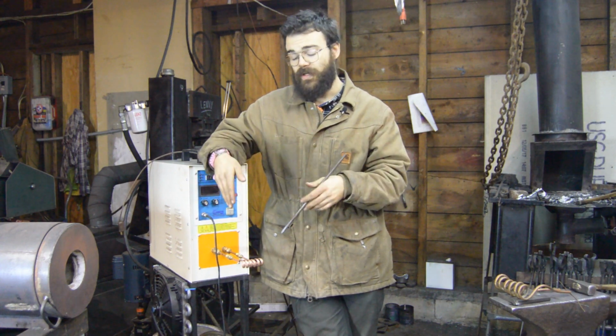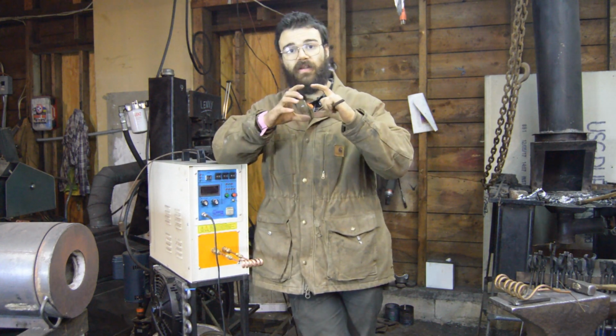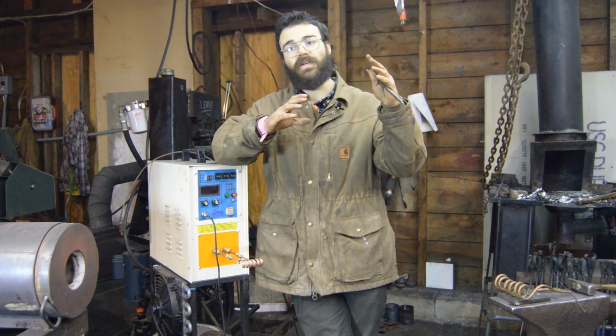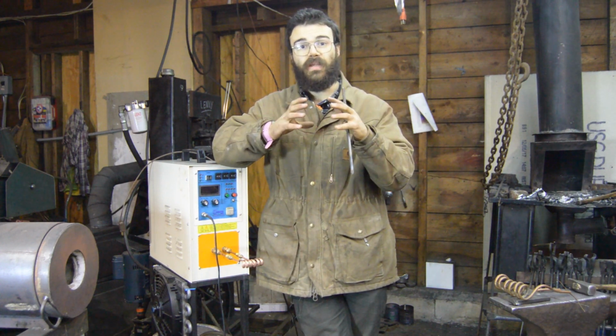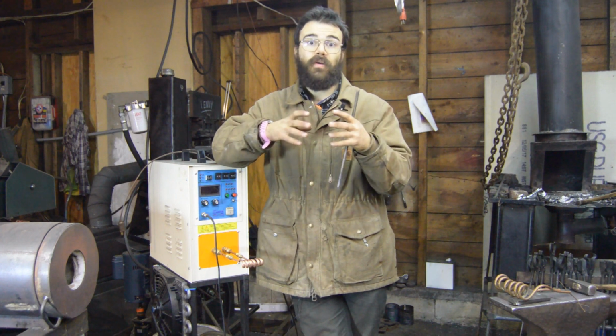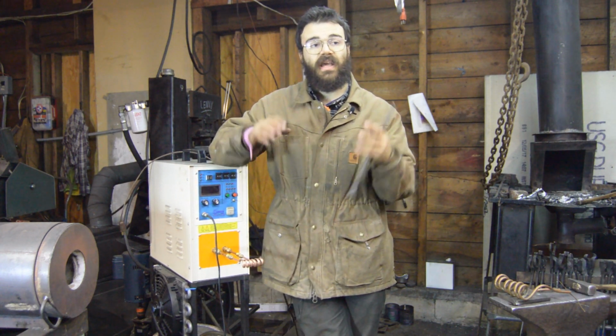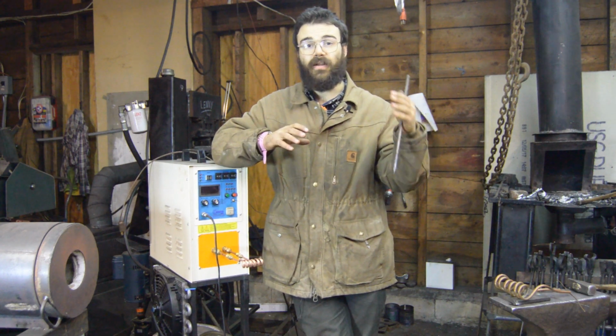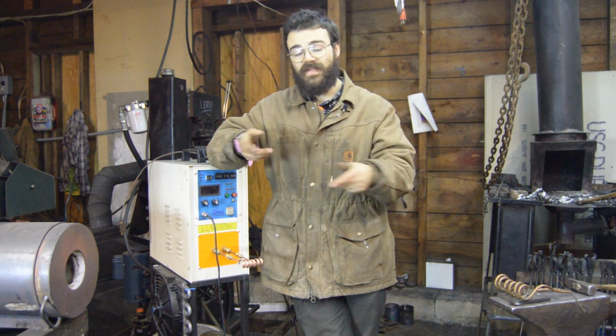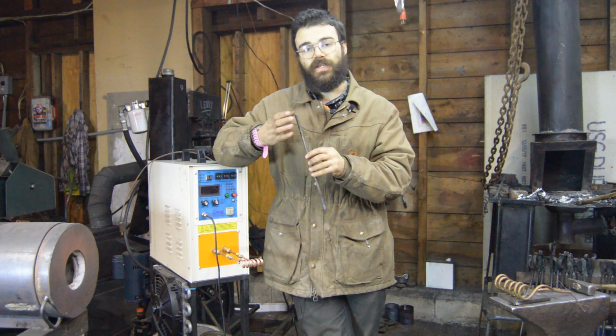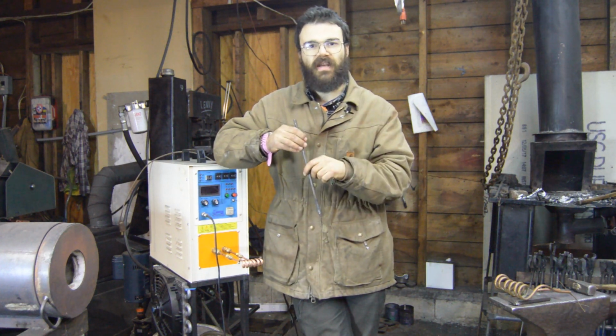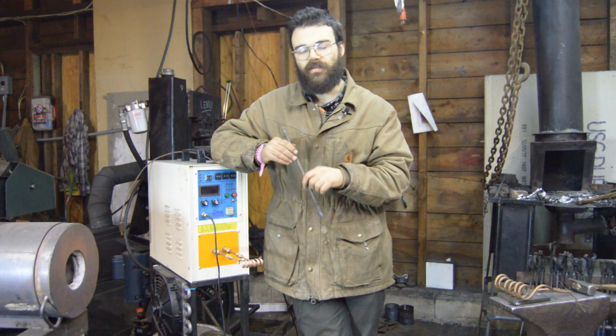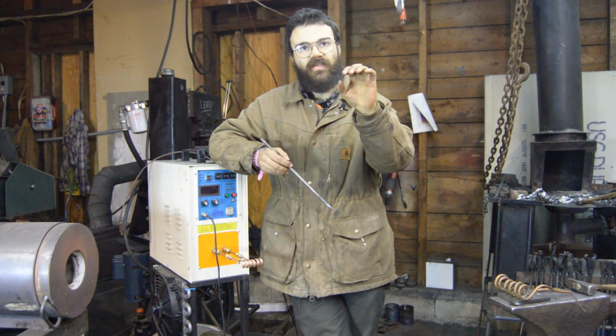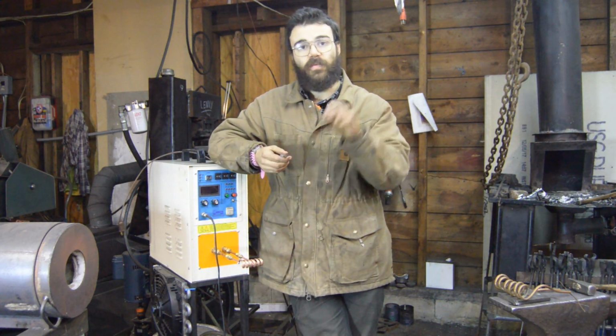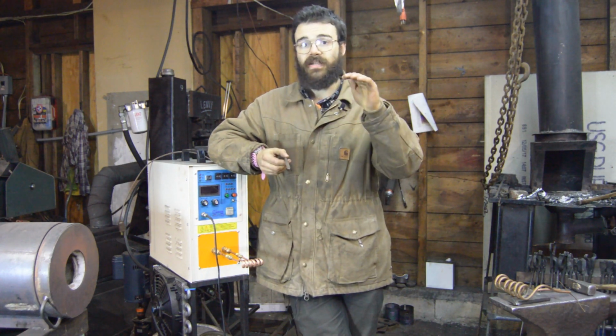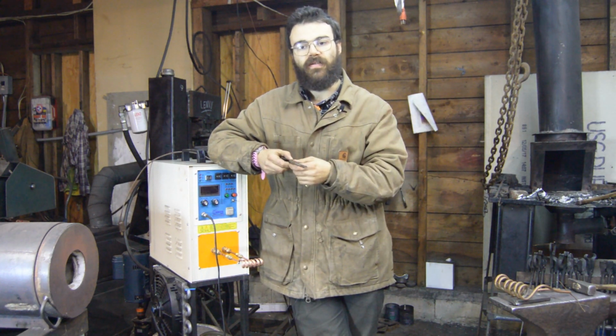So when that happens, when you're induction heating, that shell of heated material passes its Curie temperature, and then you are heating that material only in the eddy current mode. So you lose one of your two modes of heating, and that outer shell from that point onward will heat a little more slowly. When that happens, the shell inside of that, it's usually about a 32nd of an inch at the frequency ranges that are generated here. So the next 32nd of an inch shell of the material along its cross-section will start heating very rapidly until it hits its Curie temperature, and so on until the center of the bar.